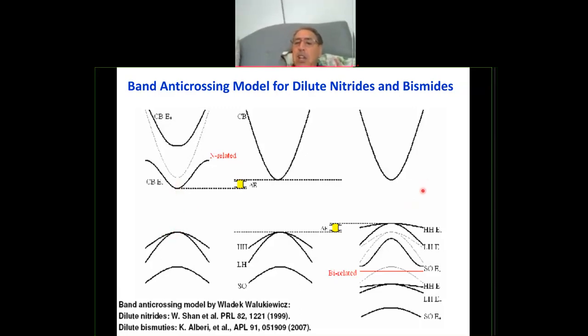When you put in bismuth, actually it's different. Bismuth doesn't affect the conduction band, but affects the valence band. You see, and then it pushes the valence band up. So that's how we reduce the band gap. So by using a combination of nitrogen and bismuth, you can tune both the conduction band and the valence band to reach 1 eV.